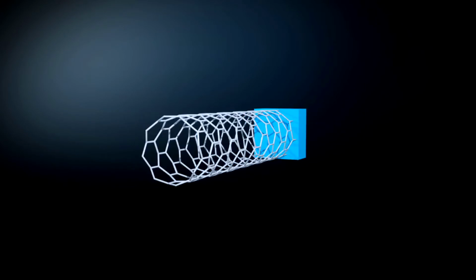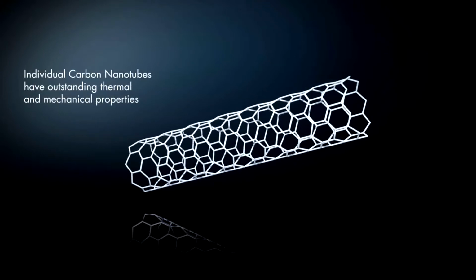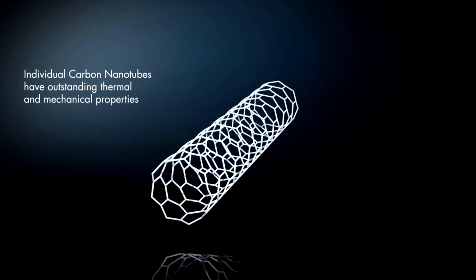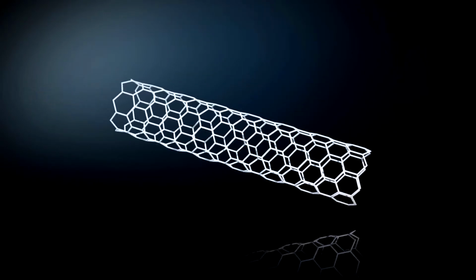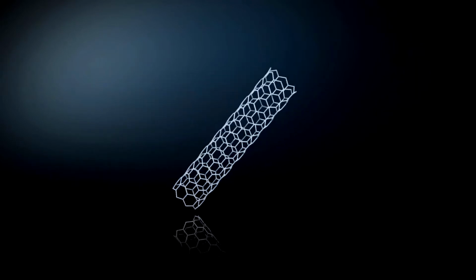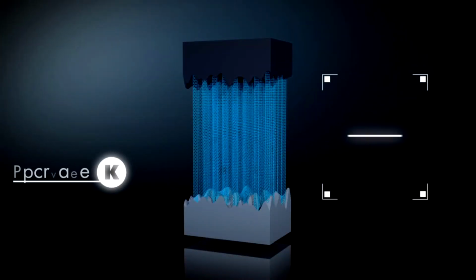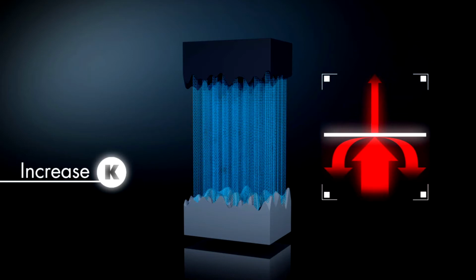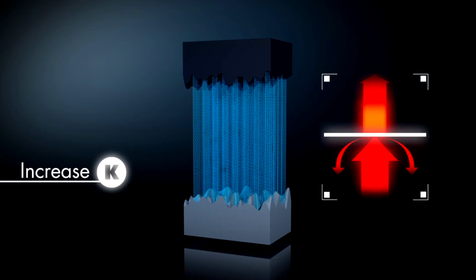Carbon nanotubes have been shown to possess intrinsically extremely good thermal performances, such as a thermal conductivity as large as 3000 watt per meter Kelvin in some cases. In NANOPACK, Thales Research and Technology investigated the crucial issues of the growth of dense areas of vertically aligned carbon nanotubes from bottom substrates, the infiltration of diverse materials between the tubes, as well as the connection to the top substrates.